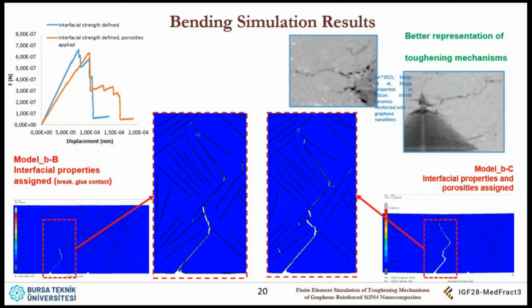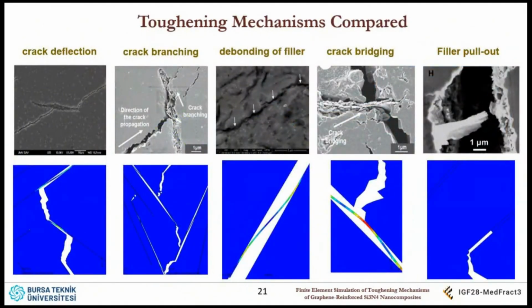So these results tell us that there are pre-cracks and they have fundamental effect on the mechanisms. And these are the comparisons of bending plots. So force displacement plots of the bending simulations. This one has got higher toughness, as you can imagine. So when the toughness mechanism compared, I could simulate almost all mechanisms.